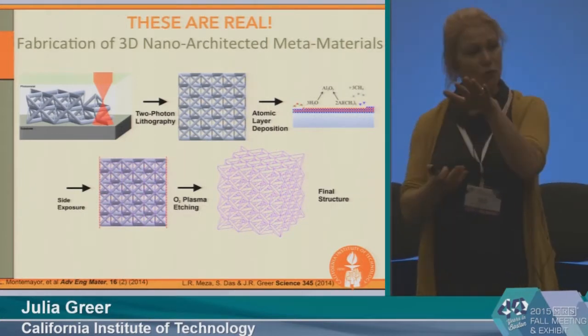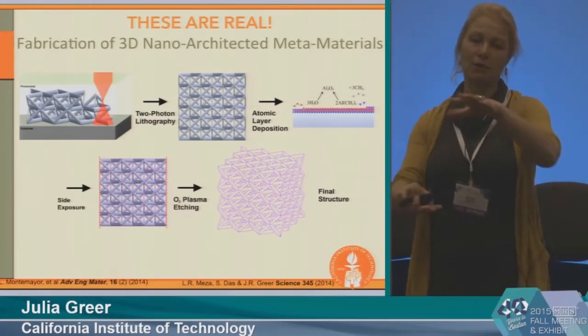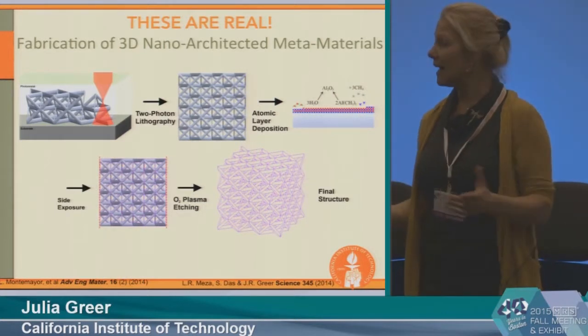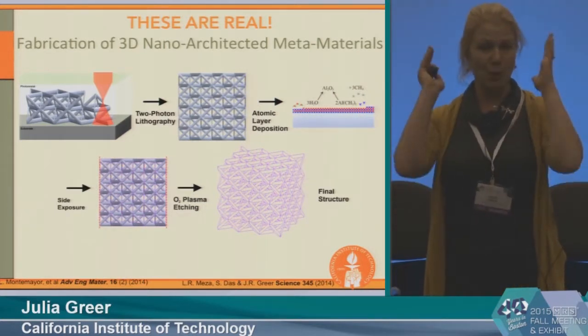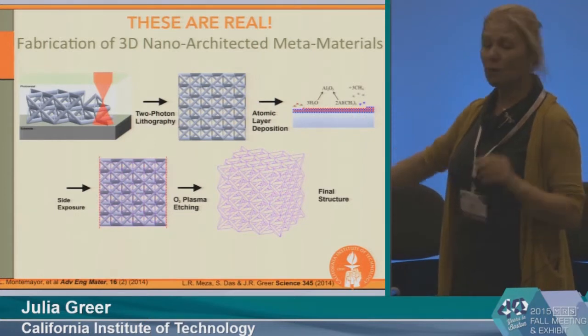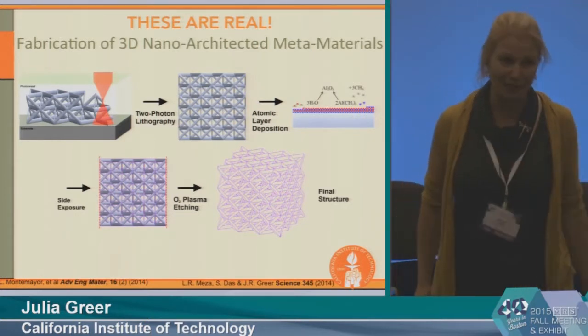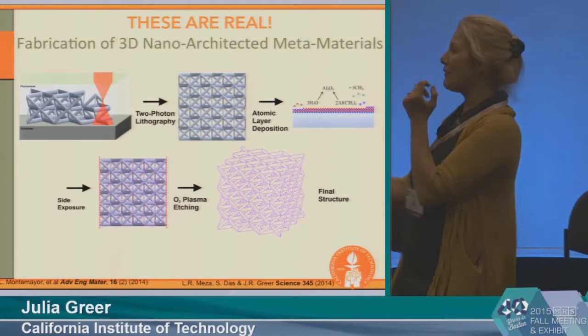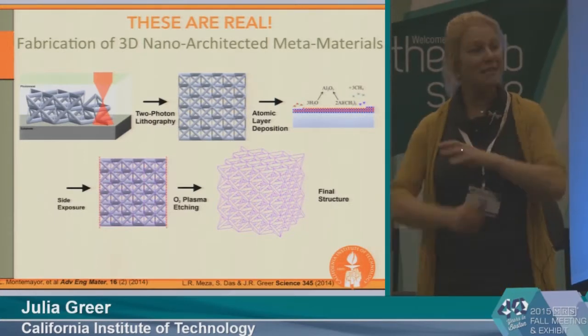And what we do after that, usually our samples are made in these cube type configurations, maybe 100 by 100 by 100 microns. And out of the 6 faces of the cube, we expose 2 of them. And when we expose them, what we're able to do is etch away the entire polymer scaffold. So this entire scaffold that was so painstakingly written is completely gone.